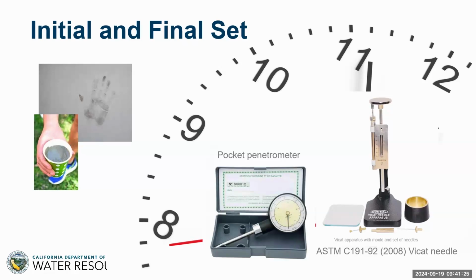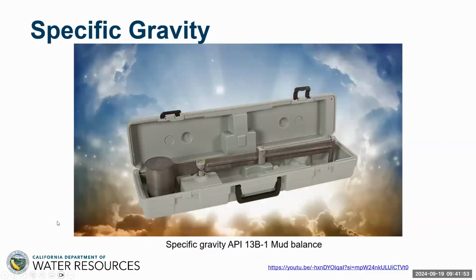You take a coffee cup, you fill it with grout, and you just watch what happens to it over a period of a couple of hours. And once you can't stick your thumb into it anymore, that's probably the initial and getting on for final set as well. So, ladies and gentlemen working in the field, I would advise you just to be pragmatic about this and just take that little cup of grout and get a good visual demonstration of what it's probably doing in the grout. Next slide, please.